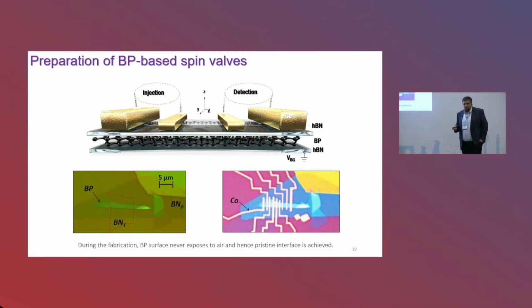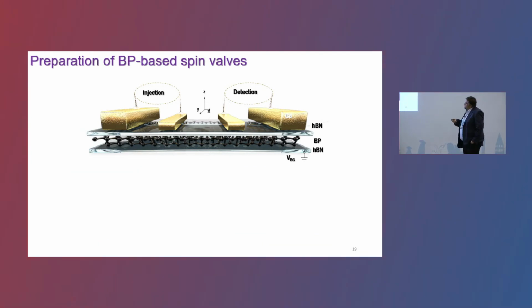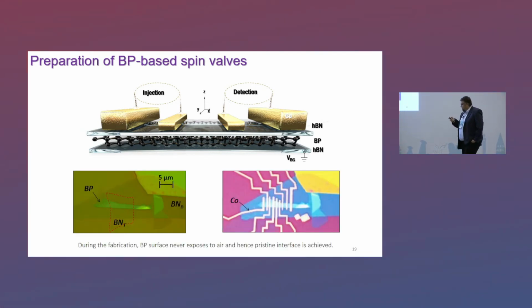And this boron nitride crystal on top is required for two purposes. The first purpose is, of course, to encapsulate it against degradation in the air. We have seen that if you encapsulate it with the boron nitride, it's very stable. And the second thing is we have a problem called the conductivity mismatch issue, meaning that if the conductivities of your injector electrode and your non-magnetic channel material are significantly different, then you cannot effectively inject a spin current into your material.